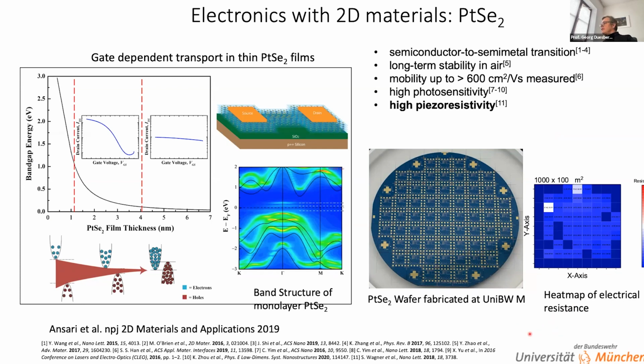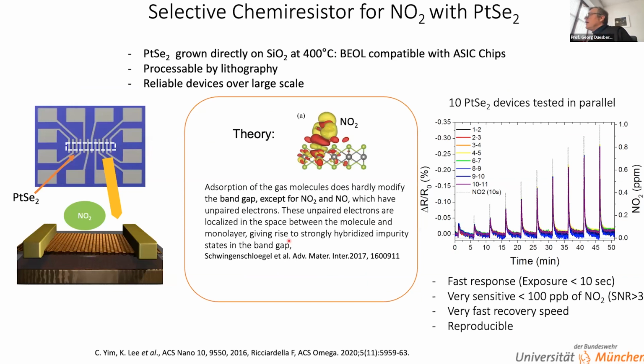And let's have a look at the applications. What I forgot, sorry: those channels have also been shown, similar to what I've shown before, not now a graphitic channel but a PtSe2 channel, to be extremely sensitive to NO2, and actually it's been shown that they are selective to NO2. Theoretically by those people, and our gas sensing results with NO2 showed extremely fast response, extremely high response, and also a very good recovery. And this is, by the way, 10 devices measured at the same time in parallel. So that's basically the gaps between those two, and they also show the very same behavior, and we could reach ppb range sensitivity for this gas.